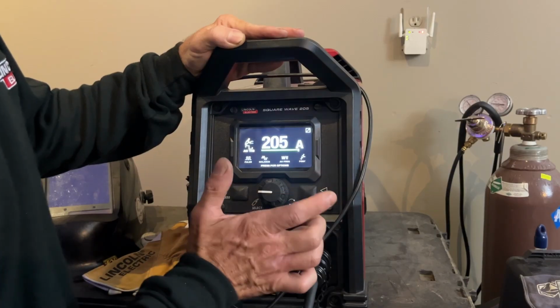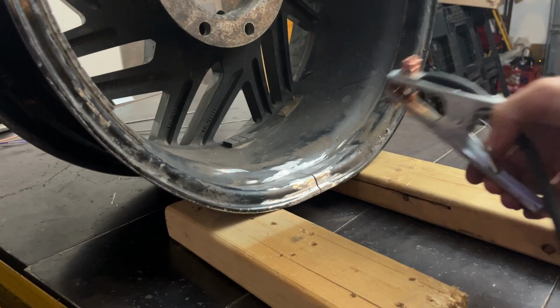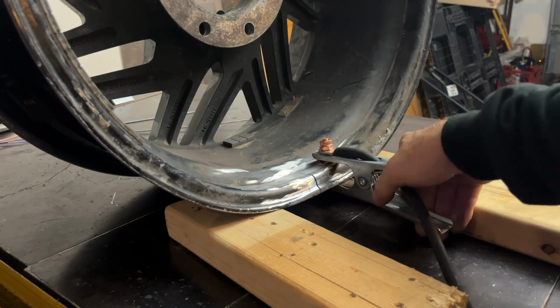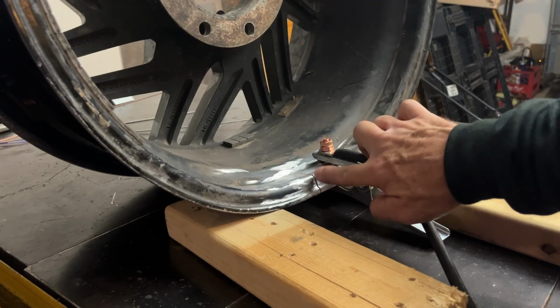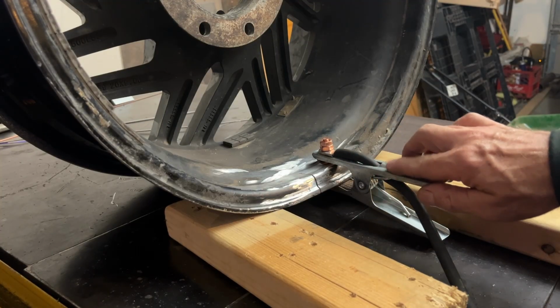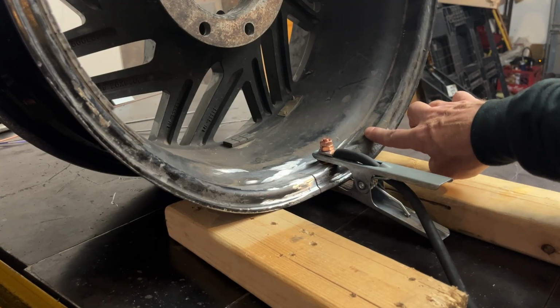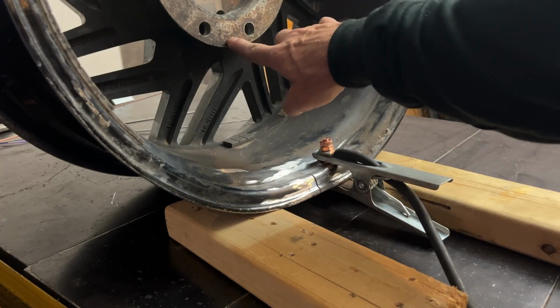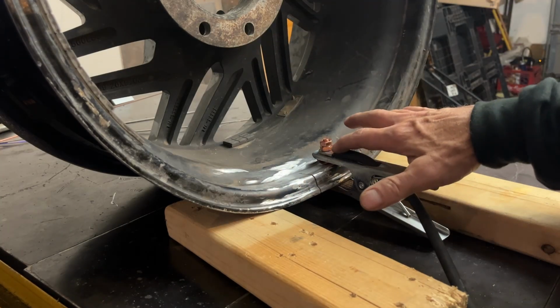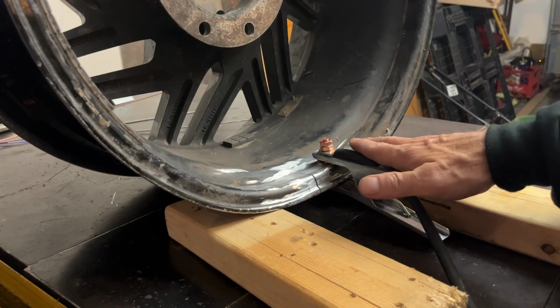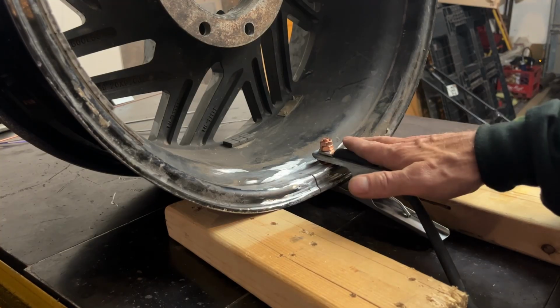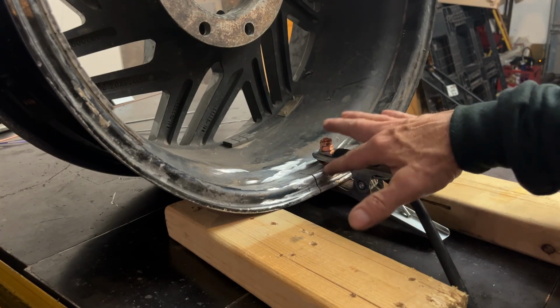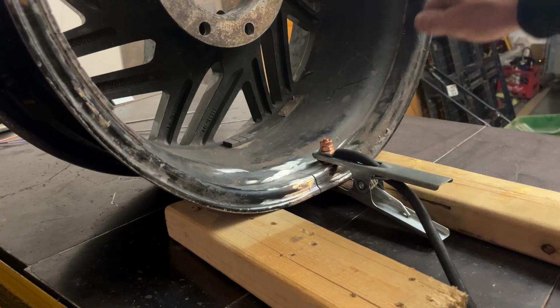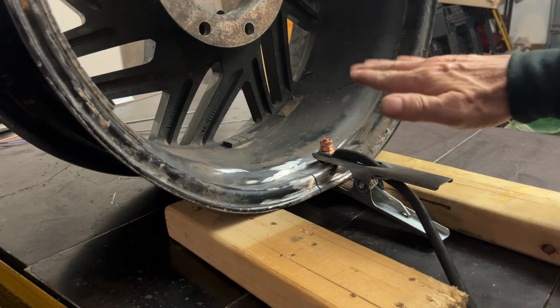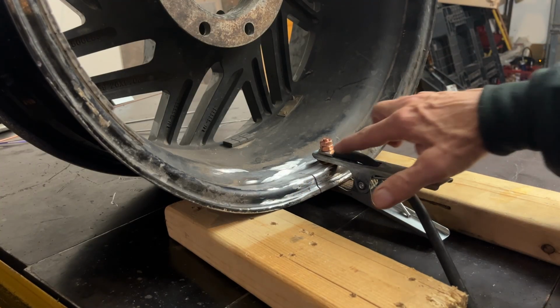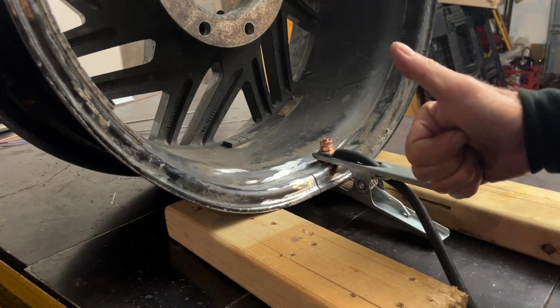Okay, let's click the back button. We're ready to weld. I'm going to put my work clamp as close as I can to the weld joint, so that current doesn't have to travel very far. At the same time, I don't want to attach through paint or any corroded surfaces because chances are it's going to arc through that paint because it's not a good conductor. Oxides are also not good conductors. So try to find some bright metal, even if it's a little bit away from the weld joint, and make sure that you're connecting your work connection to good bright metal so you have good contact.